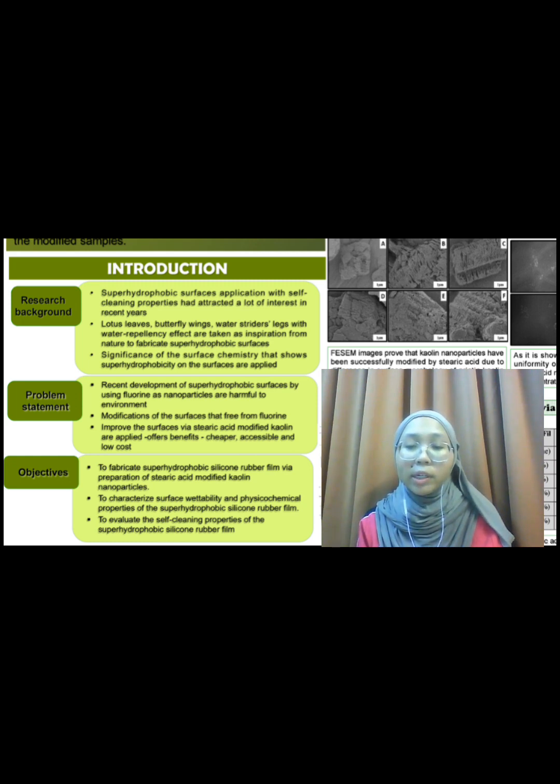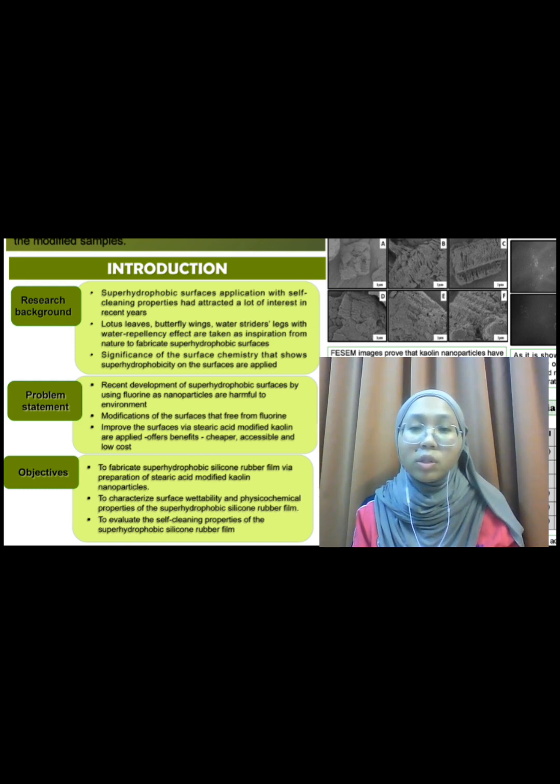By applying and elaborating this concept of the lotus leaf in the field of superhydrophobicity on surfaces, many researchers around the world highlighted the significance of surface chemistry in their research. Surface roughness together with low surface energy exhibited superhydrophobicity, where surface roughness improved the behavior of the hydrophobic surface, making water droplets become nearly spherical on the surface, while low surface energy tends to reduce surface wettability. Hence, it prevents adhesion of water onto the surface.